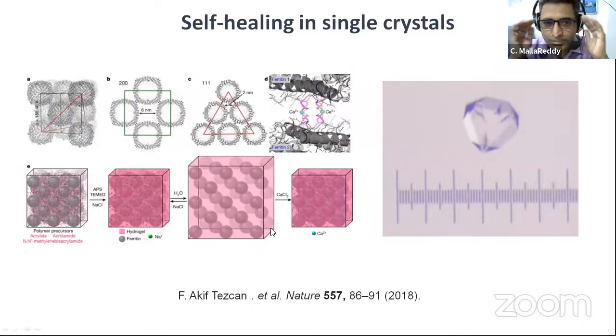And then when it comes to crystalline materials, it is a big challenge, and not much is done. There are only, as far as I know, 3-4 reports. And even in all of these, self-healing happens only under very, very special conditions, and you cannot expand some of these to other materials. For example, if you see here, it is a protein and polymer composite, a kind of hybrid material. If you take these crystals and put them in a salt gradient, salt water, or I think it's a buffer, then there is swelling.